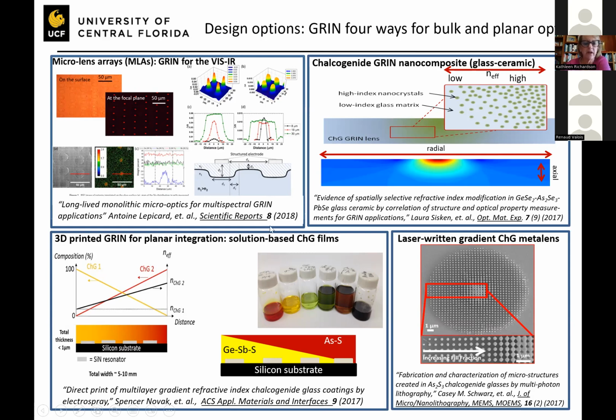We've worked hard to develop process flexibility. So all of these vials contain different glasses in solution. And we were able to, either by 3D printing or electrospray, show that we can make gradients based on changing the thickness of the layers and their composition to make GRIN this way. And this allows us now to look at one of those cross sections on our chip with our resonators and change the local environment of refractive index that our sensor sees. And that means we can sense many different things by improving the contrast and therefore the resolution of detectability or sensitivity.